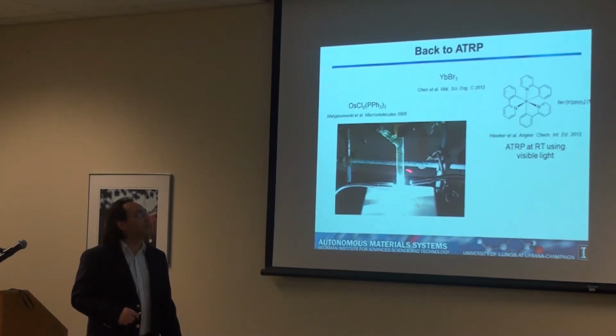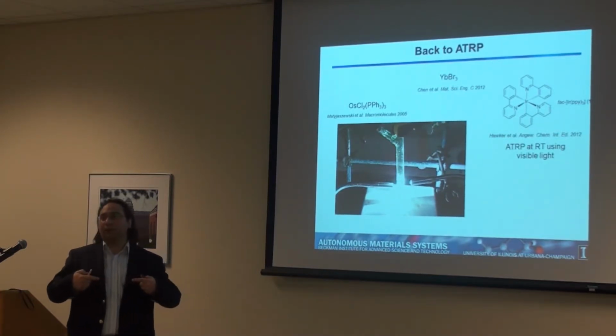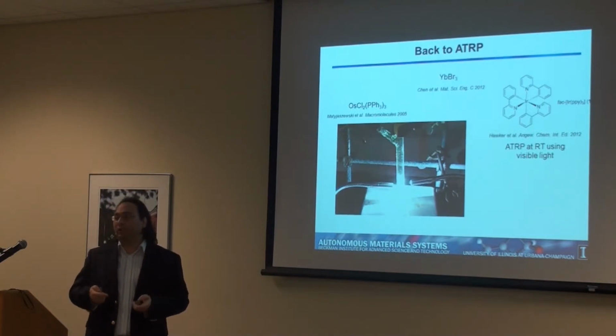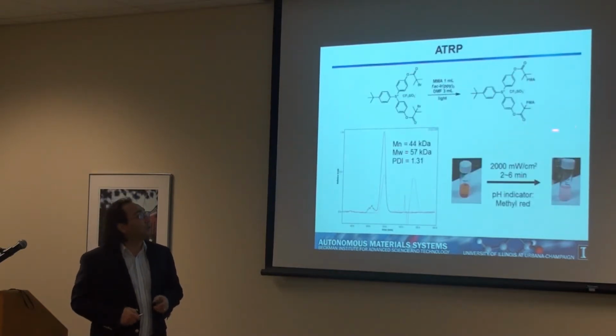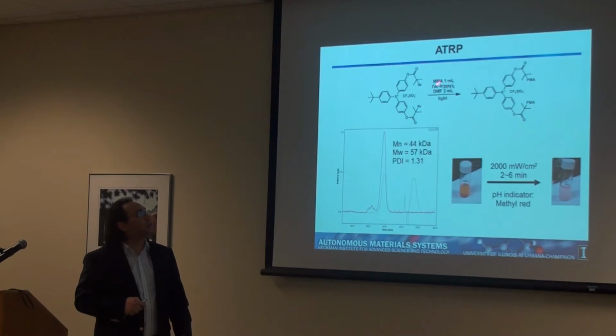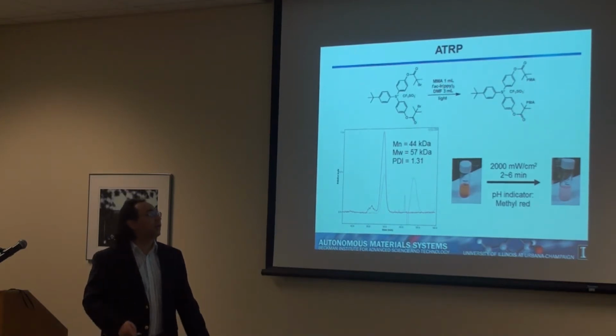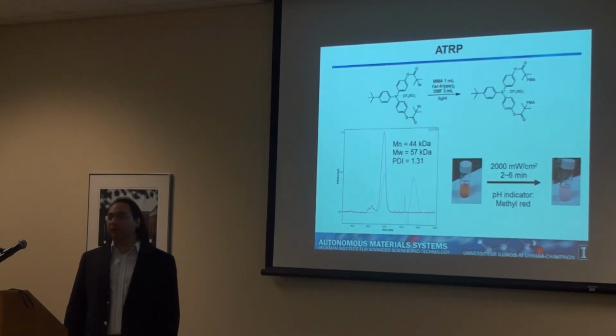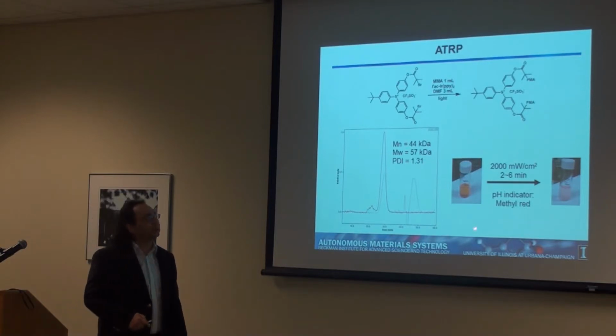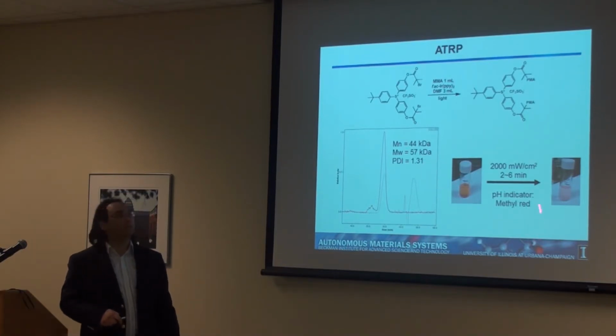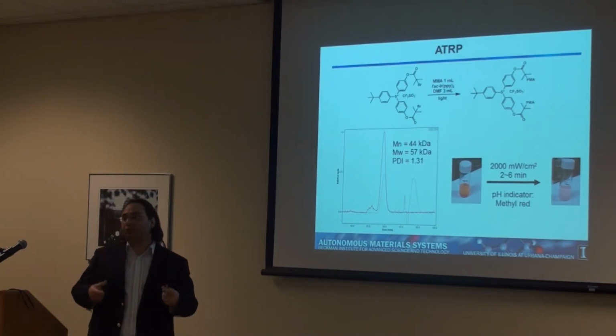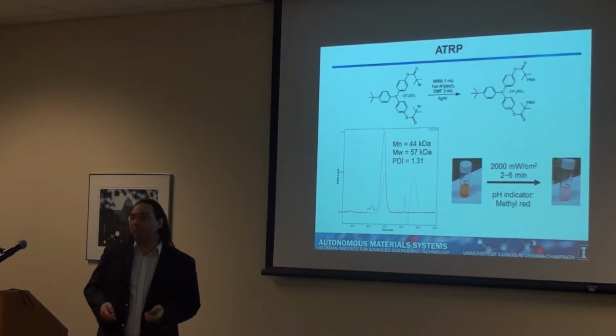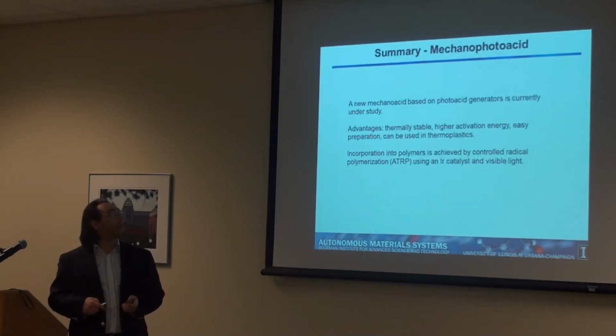So basically, you have your polymerization solution in there, and you shine visible light in it, and then you can make the polymer. So basically, you use this iridium and visible light, and you get your polymer. It gives a decent-sized polymer with good polydispersity. And again, you just dissolve it, and you shine UV light to see that your structure is still there, and you produce some acid, then it means that it's good.